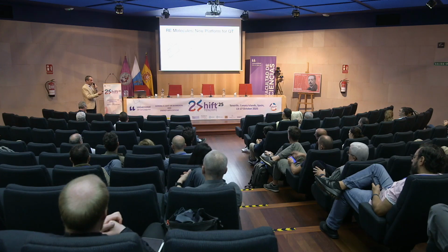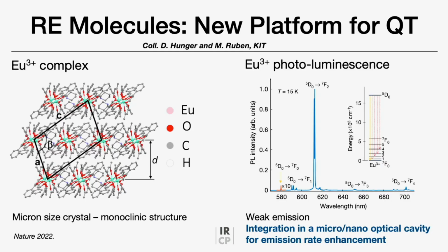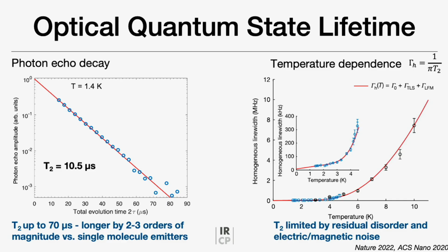But still, even with the molecule as it is, in the form of crystals and a powder of these crystals, we were able to look at the optical quantum state lifetime. It's exactly the same experiment we used for ytterbium crystals: photon echo decay, photon echo amplitude as a function of the delay between the laser pulses. Here, at 1.4 K, we were able to measure 10.5 microseconds.